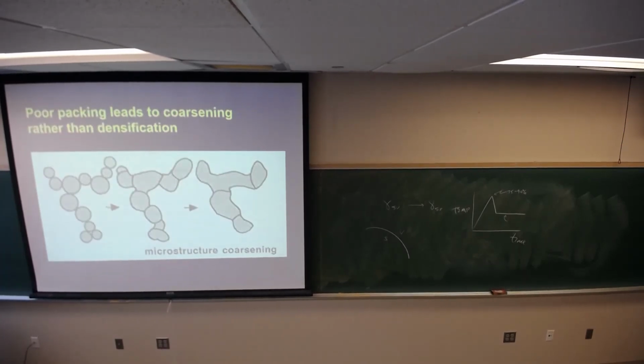Poor packing leads to coarsening, not necessarily true. What we find in sintering in ceramic systems is that the domains will sinter first. So this whole idea of slip casting and domain generation means that you will typically, in a slip cast sample, end up with a potentially larger grain size than you might predict, because those domains will sinter first, and then that remaining porosity between those domains will be eliminated. But that domain, once it sinters and densifies, now it is free to grow grains.